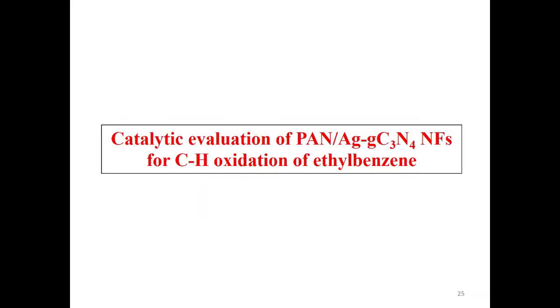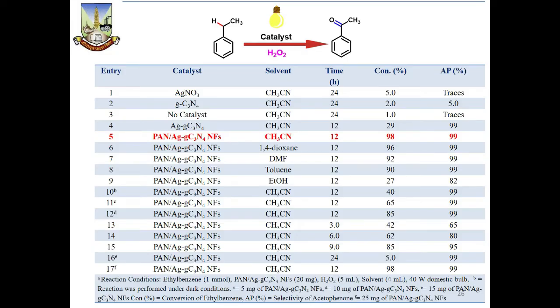Next reaction is a C-H oxidation of ethylbenzene. Here ethylbenzene is being taken. The same reaction conditions are being used, and there is a conversion taking place, that is ethyl benzene to acetophenone. The same condition is used, that is PAN AGG C3N4 nanofibers in the presence of solvent CH3CN. Time required for the reaction is 12 hours, and conversion rate is 98%. So acetophenone, 99% conversion is taking place as compared to the ethyl benzene.